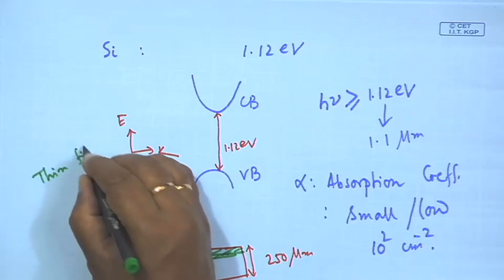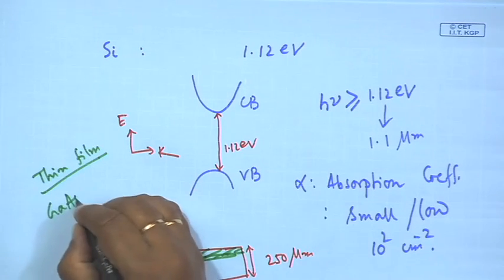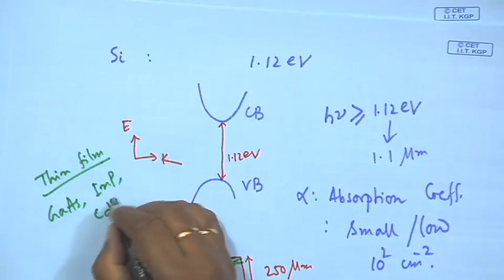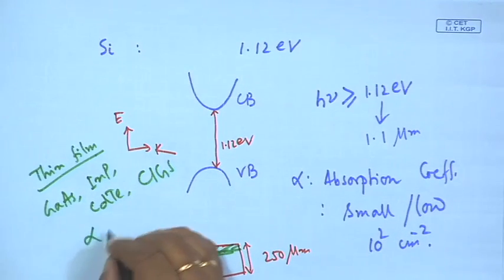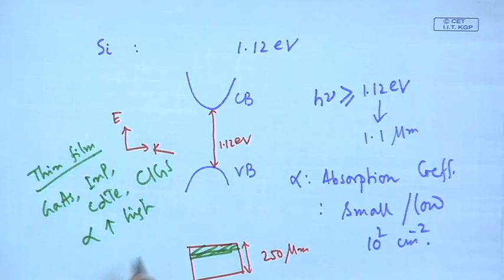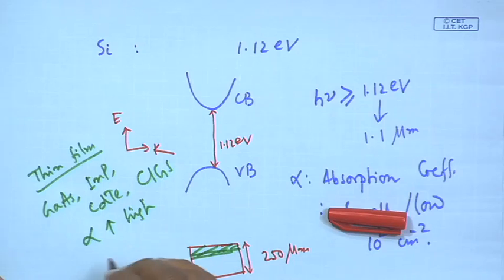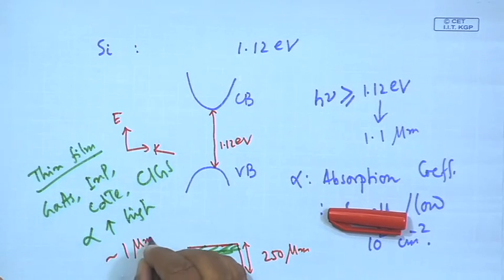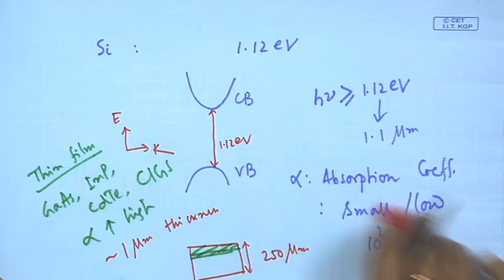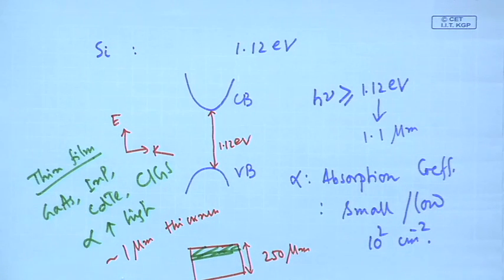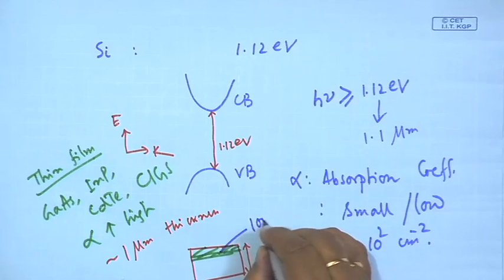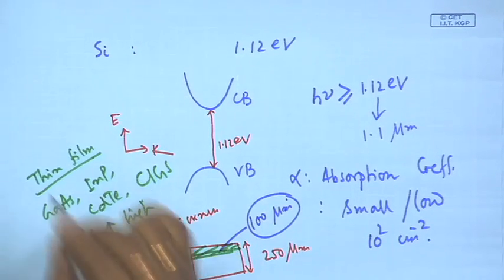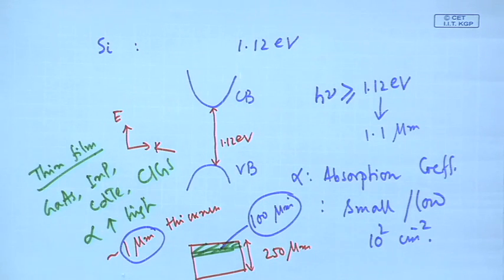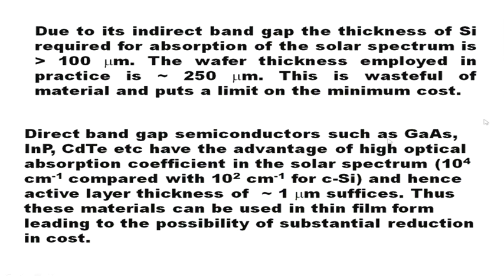then the material cost could be very less. And we know that for gallium arsenide, indium phosphide, cadmium telluride type of cell or CIGS, because its alpha is very large, high alpha, we can use a small thickness to absorb the solar radiation. Almost 1 micron thickness can be used for making this type of solar cell, whereas in the case of crystalline silicon, we know that this is almost 100 micron. So this is 100 micron, this is 1 micron for thin film, and the reason is that the absorption coefficient alpha is very, very high in this material, which is 10 to the power 4 per centimeter compared with 10 square per centimeter for crystalline silicon.